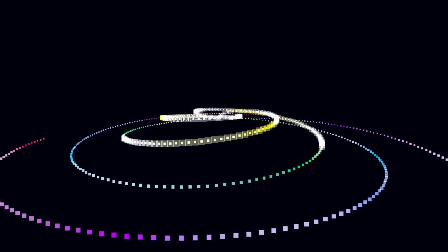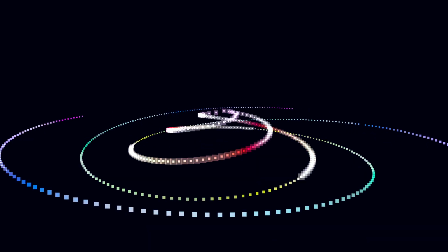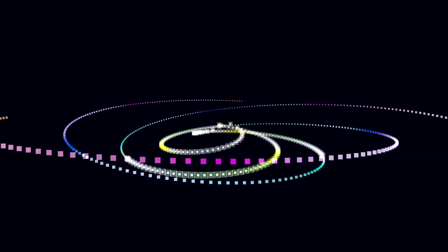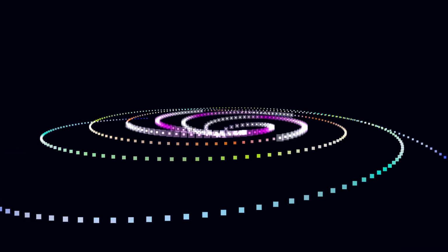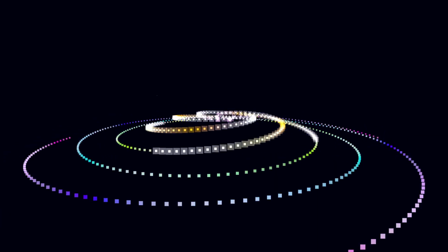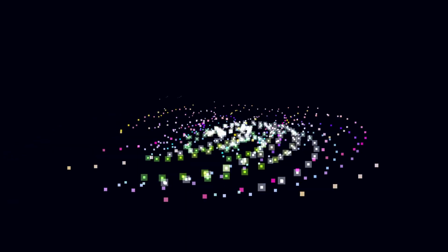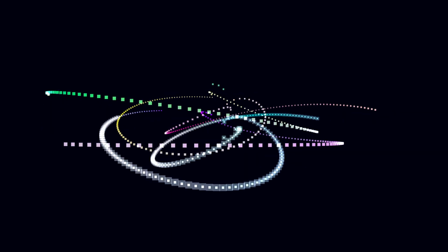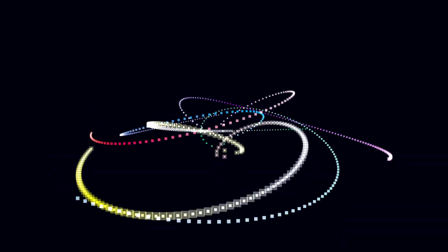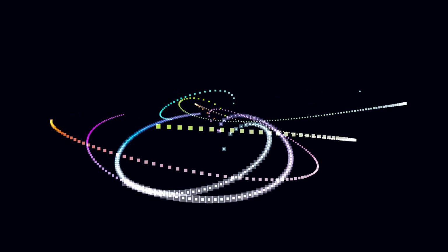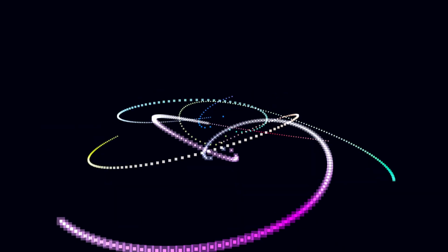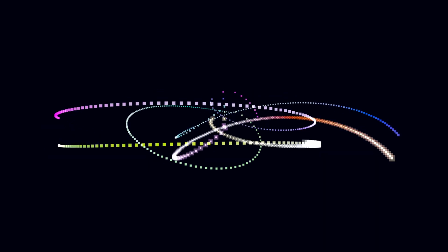What's the big appeal here? Why diamond defects? One huge potential advantage is room temperature operation, or at least much closer to room temperature than superconducting circuits need. That simplifies things enormously. Control is done with microwave pulses, similar to magnetic resonance imaging, MRI, but for a single electron spin, it's called electron spin resonance. And lasers are used for initialization and readout. The NV center glows, fluoresces when you shine a green laser on it, but importantly, how brightly it glows depends on its spin state, so you measure the light intensity to read the qubit.